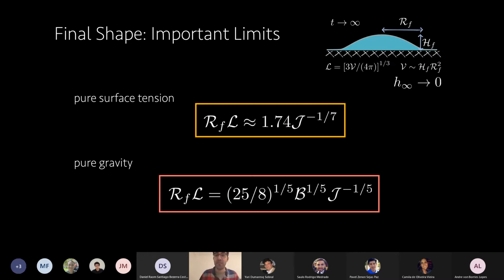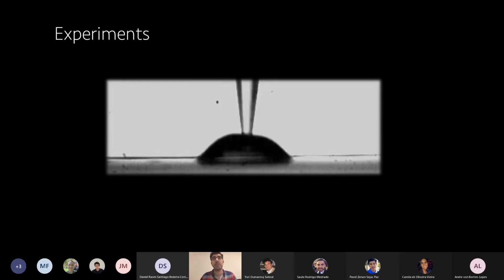theoretical analysis and experiments. We got Carbopol solution, which is hair gel. If you want to do this type of experiments, you can simply get hair gel, put it in a rheometer, and measure your material properties. So our materials are basically Herschel-Bulkley fluids, have yield stress, and these are the experiments we've done.